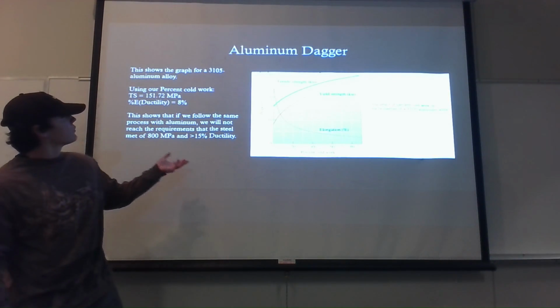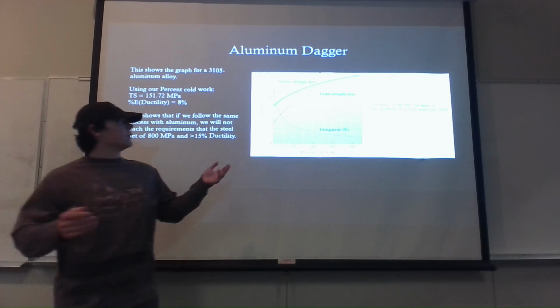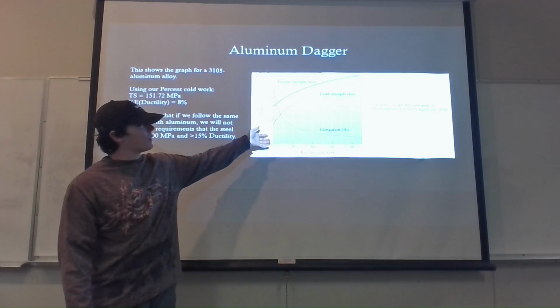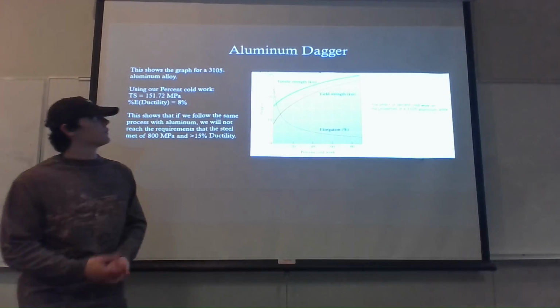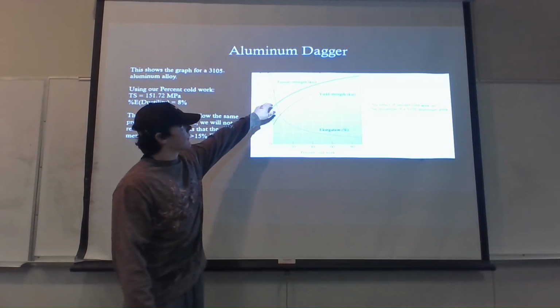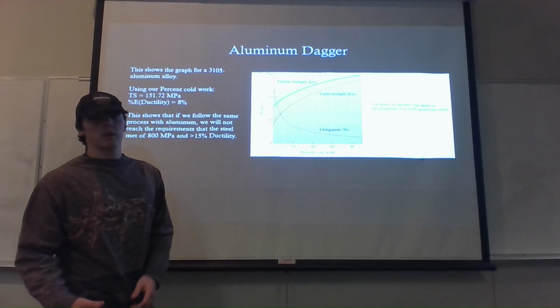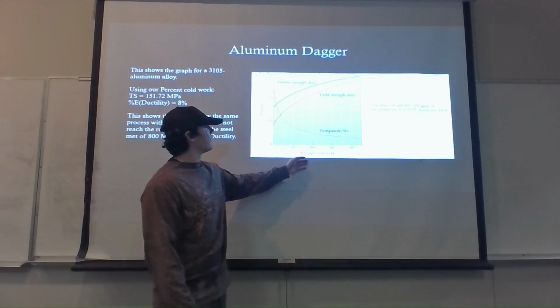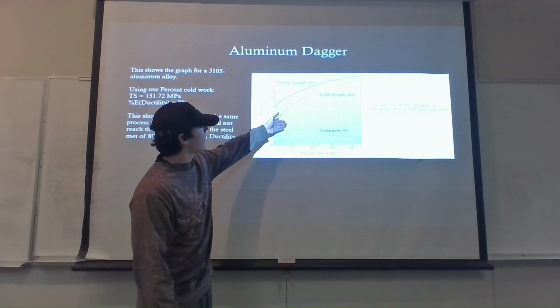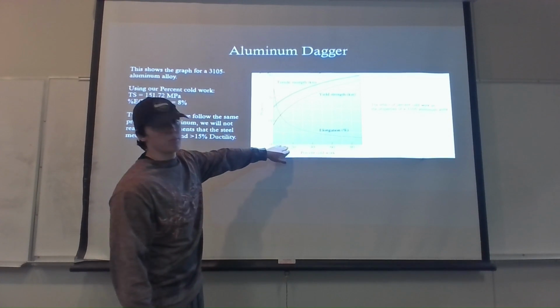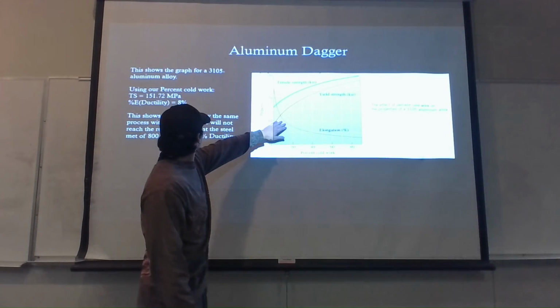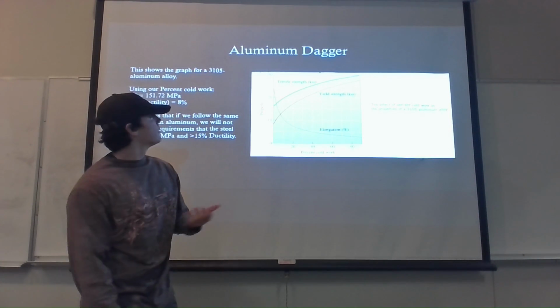Now, if we take this 13% value we found, this is the graph for aluminum. So it's different than steel, so the values are going to be different. This is in KSI, so we just have to transfer that to megapascals in order to find out our work. But if you look at the graph for the percent cold work, if we take our 13% that we found for the cold work, and we just follow it up along the graph, we'll find that if we did the same process for steel, or for aluminum, sorry, that we did for steel, we'll only get around an 8% ductility compared to the 15% that we had within steel.